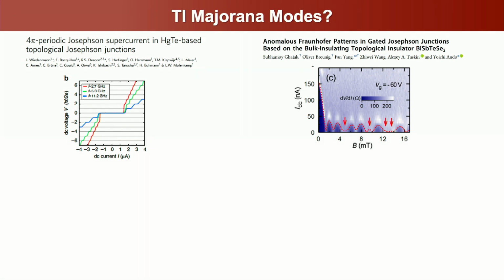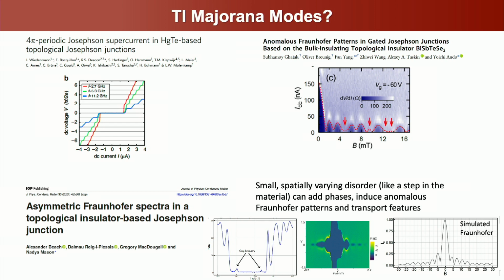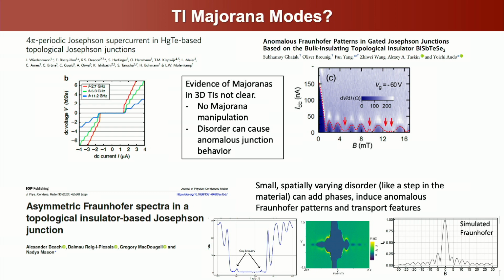But we recently published a little paper where we took a topological insulator Josephson junction that had a step function in it. Basically, it was a film of TI, and it had a thickness step. What you can show from the simulation is that just from one step in the thickness alone, you can get all the asymmetries that people have seen before that they associate with Majorana modes. You can get lifted nodes, you can get asymmetries. And so it turns out for most of these measurements, it's really difficult to distinguish between disorder-induced anomalous behavior and Majorana-induced anomalous behavior. And I think that's a controversy that just hasn't really been solved yet.